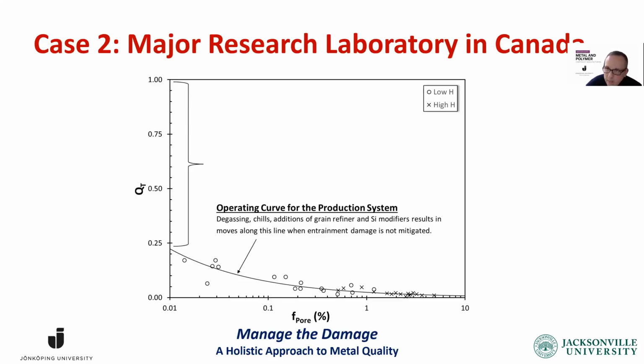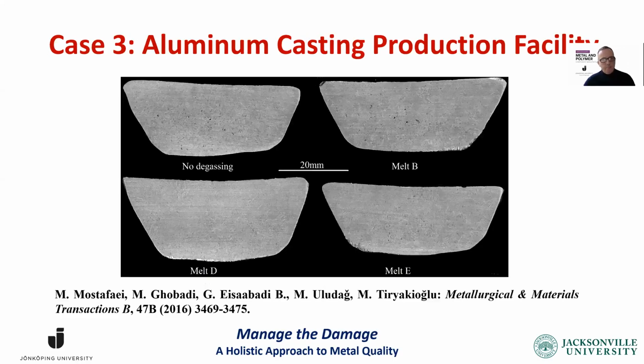But the main message is that even when we do our best, meaning the y-intercept, there's the inherent damage in castings due to the production system. And in this case, we're losing about 77% of the potential of aluminum based on the entrainment damage. Okay, this comes from a real aluminum casting production facility.